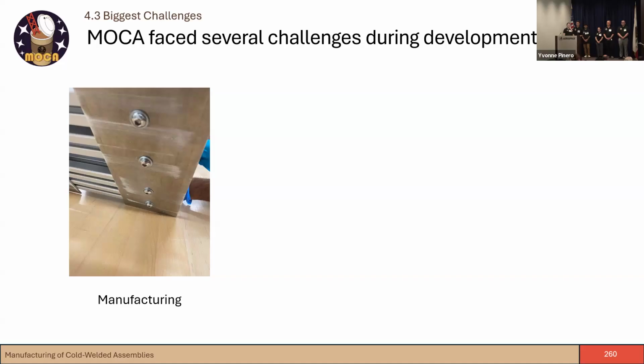For instance, with this plate depicted here, we intended to use countersunk screws to keep the plate flush with the ground. Unfortunately, the plates were not thick enough to prevent these screws from protruding through the plate and causing several stress points to form on the bottom of our extrusions. So to fix this, we switched to button head screws and washers in order to help support that better. Next, please.